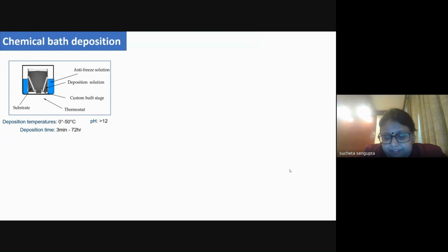To fabricate these heterostructures, we have taken help of chemical bath deposition. It is nothing but a beaker where we put the substrate, and in that we put the deposition solution with the precursor material. Suppose we are synthesizing cadmium sulfide, we put the cadmium precursor and the sulfur precursor, and we put it in a water bath to achieve the temperature. The deposition temperature can be varied from 0 to 50 degrees centigrade, and the deposition time we vary for several hours according to our wish, and the films are grown over the substrate in this way.